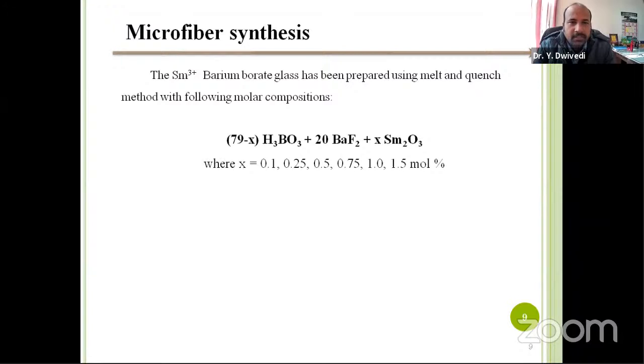Let me start this microfiber synthesis. For the synthesis, the sample is very simple: we have H3BO3 as a network former, and barium fluoride as a network modifier. We have tested this several times, so nothing to worry about. This always forms a very good glass material.